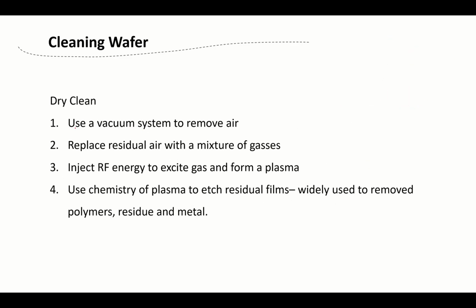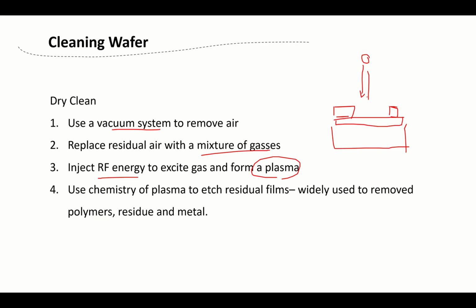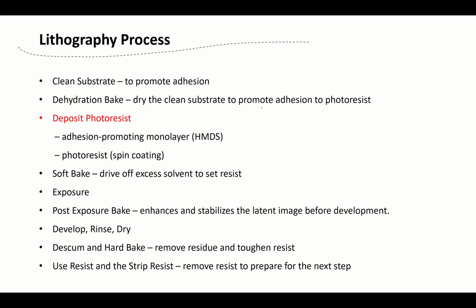For dry etching, first we remove the air in the vacuum system. Then we put in a mixture of gases, then we inject RF energy to form the plasma. So if this is a PR, and here is the part you want to etch, and here's the wafer, the plasma will be over here, then it will shoot the plasma on it to etch away this part. It can be used to remove polymer residue and metals. Oh, sorry, this is etching, but it's the same idea; in here we will just do cleaning, not etching, my bad. After the cleaning, we do a dehydration bake to remove all the moisture. Then we start depositing the photoresist.